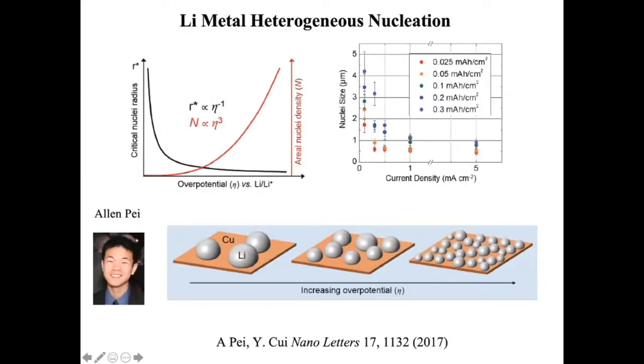So speaking of that, if we think about lithium plating and stripping, do we really understand? I mean, the first thing you need to face is the nucleation, particularly if you start with something like copper foil as a current collector and you deposit lithium. What's the behavior of that? Allen Pei, my graduate student back in 2017, together we published this paper, right? This is a very classical heterogeneous nucleation problem. You deposit lithium onto copper. They have different crystal structure, different lattice spacing, and they don't necessarily like each other. And lithium would require a nucleation barrier right there.